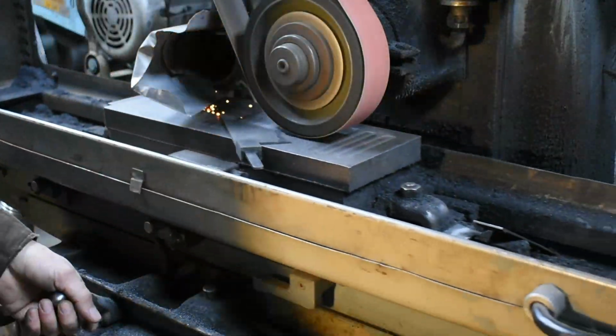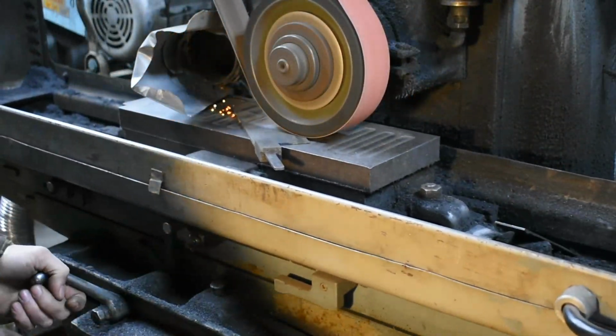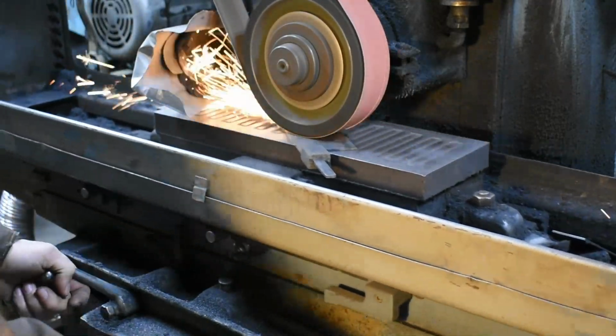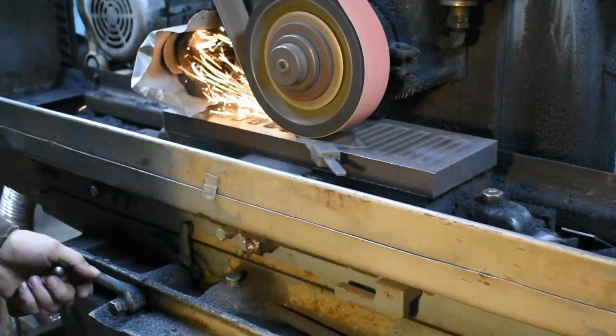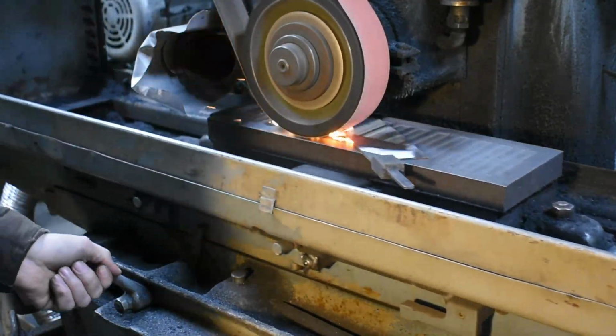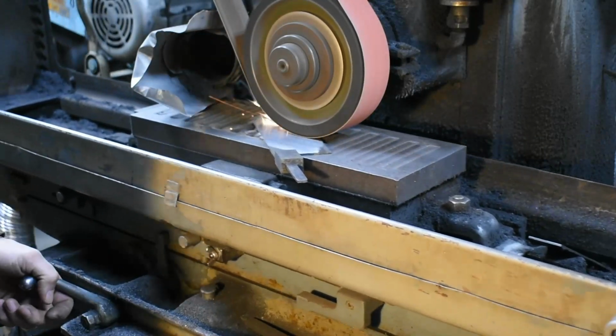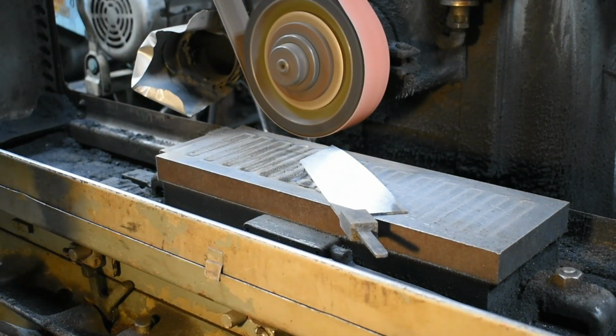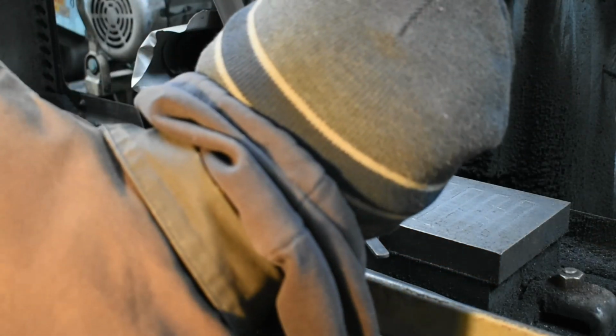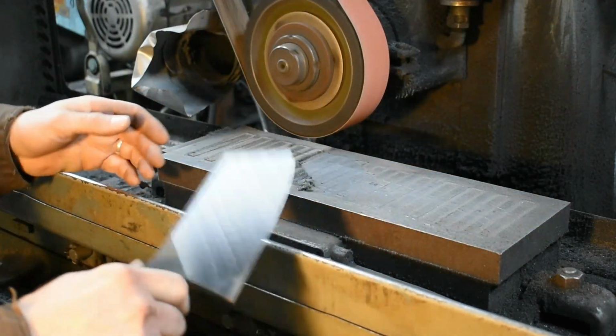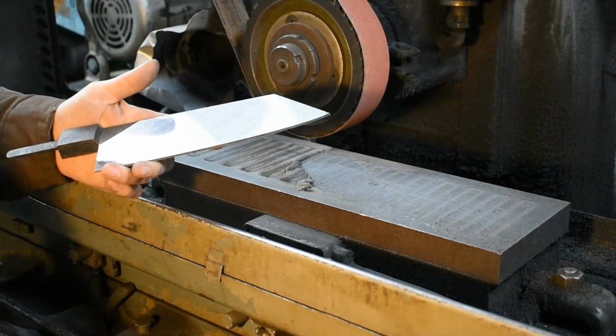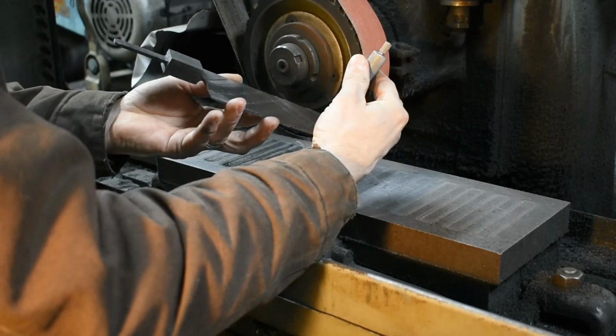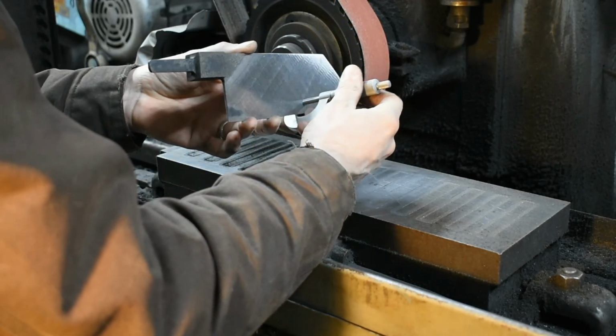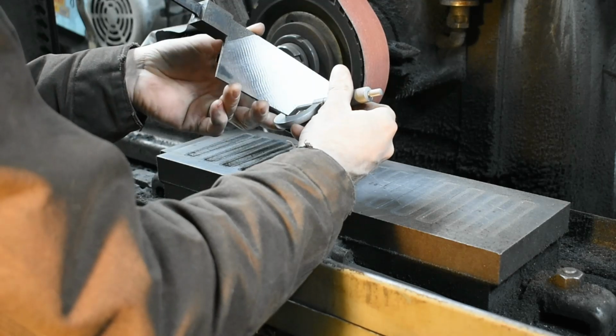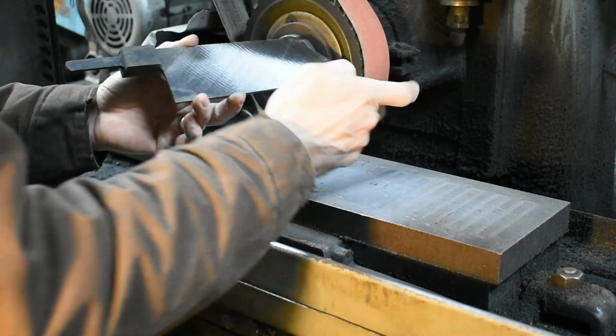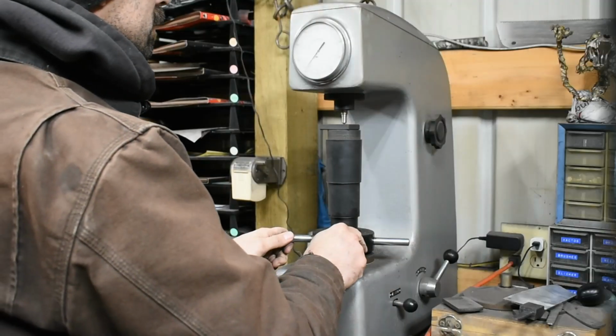I put them at an angle on the chuck there, of course, because I can't be running into the bolster. And I want to get the whole blade on the chuck as much as possible up to the bolster. And then I'll just grind that remaining little triangle off in front of the bolster on both sides. There's my 120 grit on one side. And that'll bow it like a banana, taking that decarb off one side all at one time. Enough to freak you out, but so I'm checking my thickness just to see where I'm at. And then I'll take that 5 thou off the other side, and it'll bring that warp back out of it.